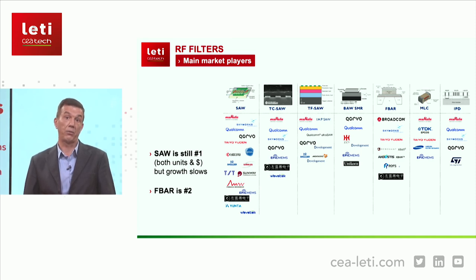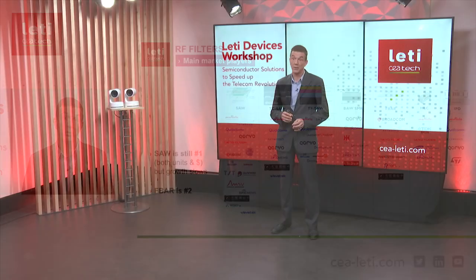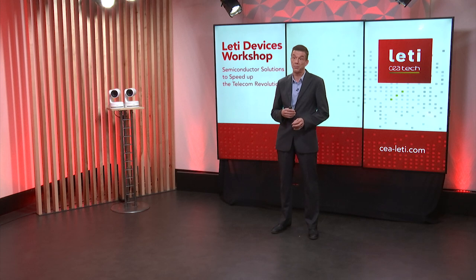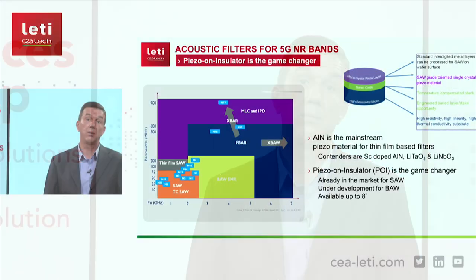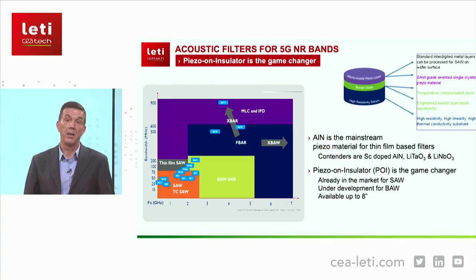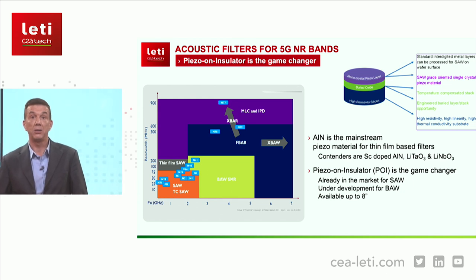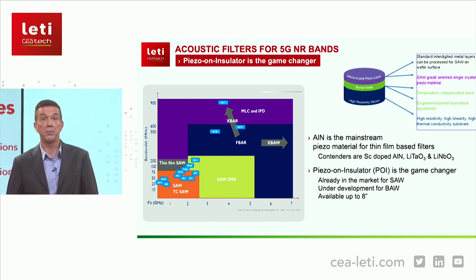In these devices, the piezo material is typically aluminum nitride. It is deposited on the substrate, and the acoustic properties of the piezo layer are tightly coupled to the crystal quality of the thin film layer. Consequently, a lot of effort has been invested into better deposition methods. These efforts are ongoing with aluminum nitride and scandium doped aluminum nitride. However, an alternative called POI has appeared recently.